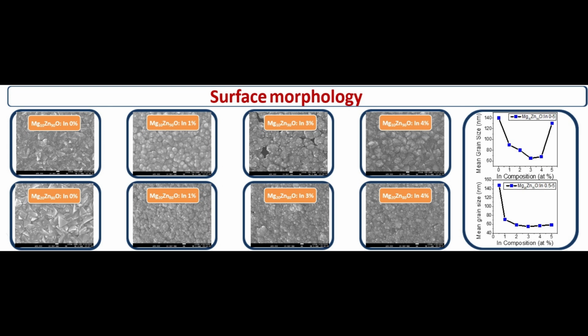Assessment of magnesium zinc oxide samples doped with indium was studied. 99% magnesium acetate tetrahydrate was applied in a 10 and 20 atomic percent content as magnesium precursor, and indium contents of 0 to 5%. After the films were deposited, a thermal annealing treatment at 350 Celsius degrees for 3 hours in a nitrogen flow of 8 liters per minute was done.